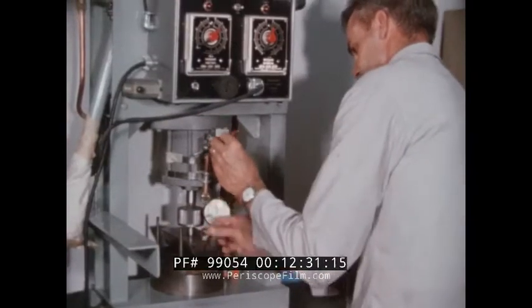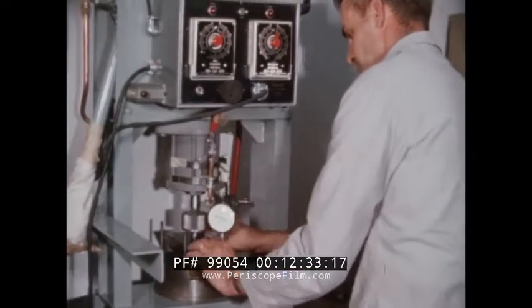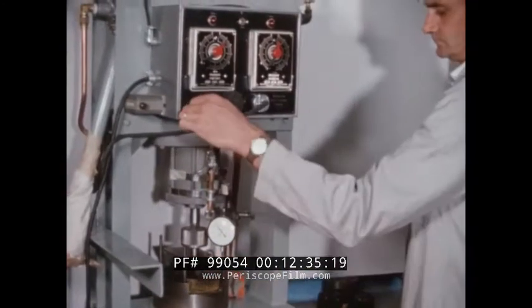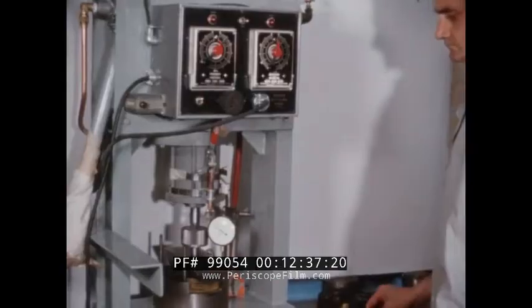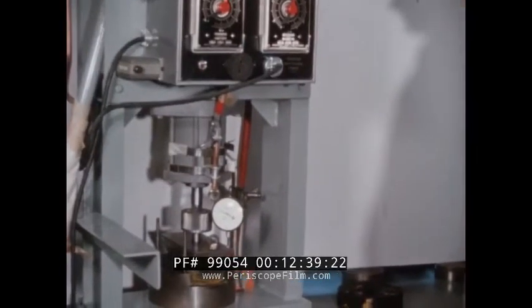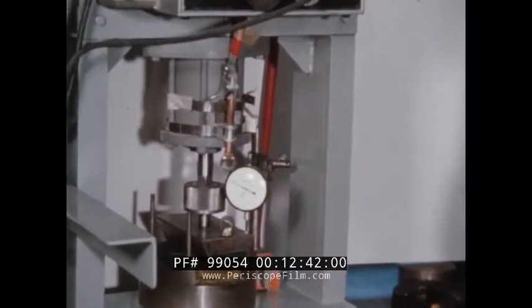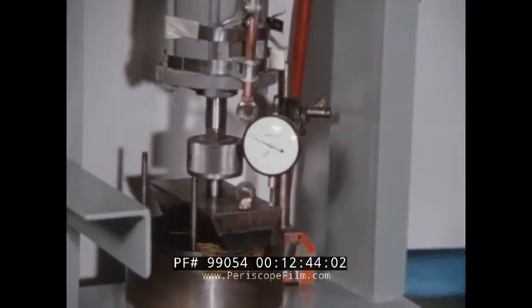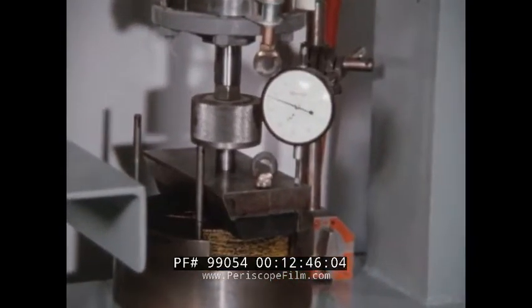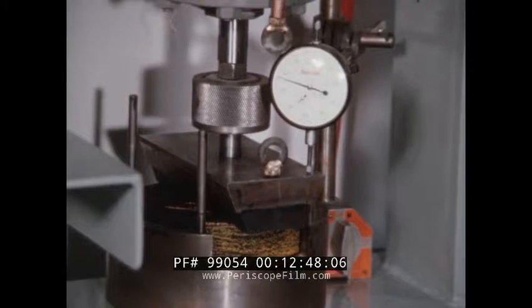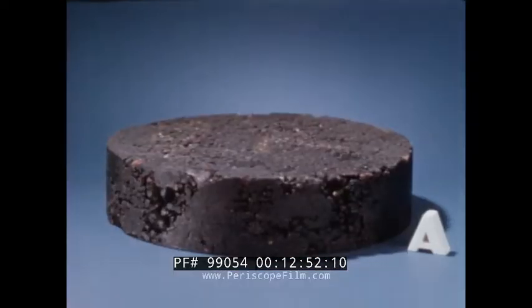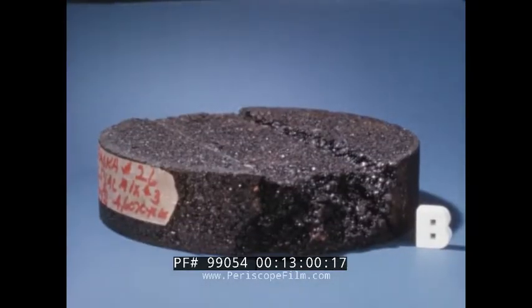The behavior of asphaltic mixes under simulated traffic is analyzed in repeated loading devices. The degree and duration of load can be varied to duplicate traffic conditions ranging from residential streets to busy expressways. Sample A shows the successful performance of an asphalt mix under 20,000 load cycles, while the standard B mix failed.